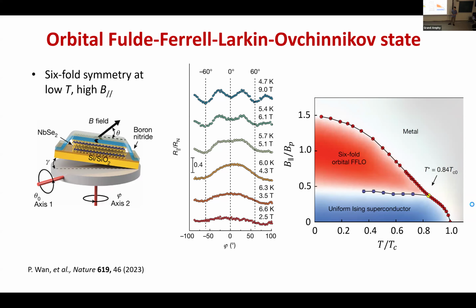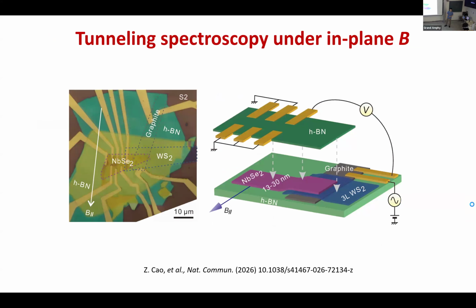So is there any hysteresis, since it's supposedly first order? Recently we got something, and we believe it's a first order transition. Yes, just in a minute. So why do we have this bend? It kicks up only at lower temperatures. The argument is that you transition to another state, and this state helps you to boost the critical current. So the critical current usually drops down like this, and then up to this point you go into another state, so the critical current can survive for a larger field.